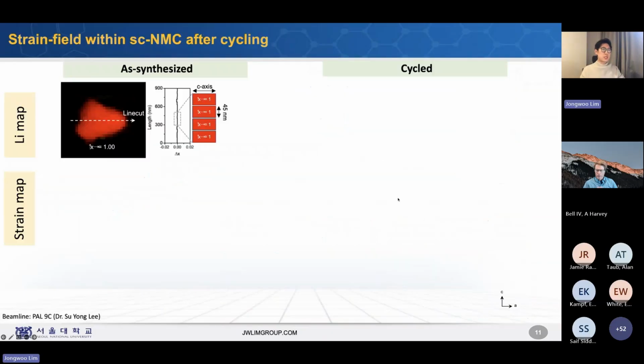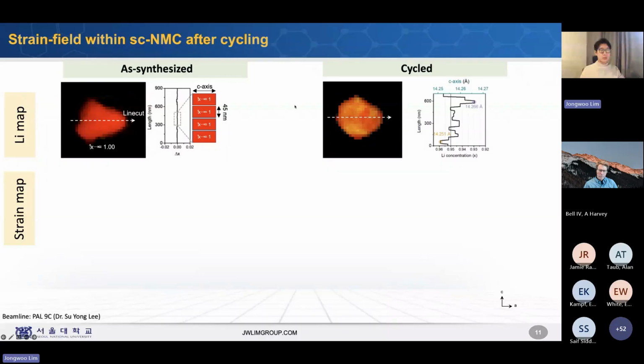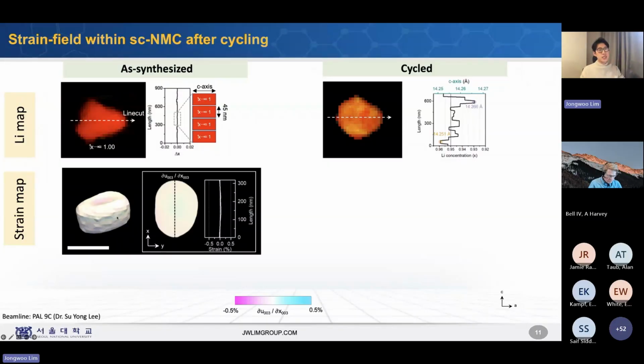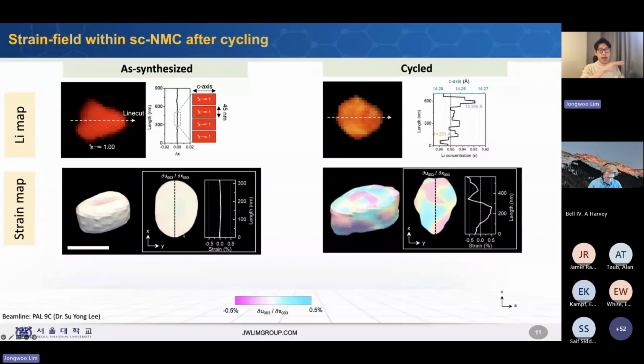And what we do here is this: as a synthesized particle, we anneal at 800 degrees, making sure that everything is so flat. Lithium concentration is so homogeneous. And this is one of the particles we cycle. We fully discharge, fully lithiate them electrochemically. And then, however, there is still a little bit of lithium fluctuation, maybe like 5% fluctuation. This is something that is almost inevitable, as I mentioned before. As a synthesized particle, we don't see any strain information. We don't see any strain fluctuation at all. It's all flat. However, that fluctuated lithium distribution then results in Bragg coherent diffraction imaging showing there's a 0.5% strain fluctuation out there.